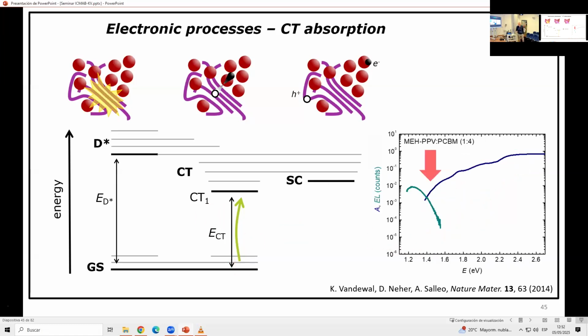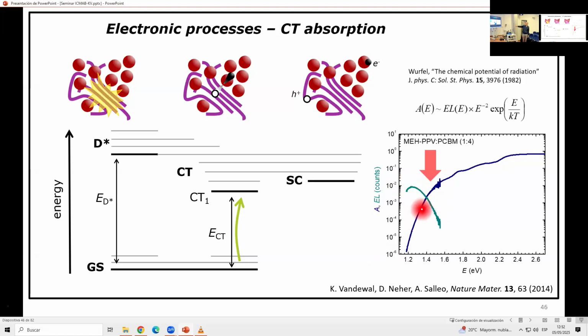And then, if you excite it directly, I also showed you in the detector in the previous part, you can make free carriers. You can see this here. Here's the emission spectrum on a logarithmic scale. Here's that absorption spectrum, with this part being that CT absorption. It doesn't look like it's at the same energy. But if you know an emission spectrum of something, you can calculate for that same state what the absorption spectrum would be with a rather simple formula. And if you do that, you see that that emission really comes from that thing which was absorbing.